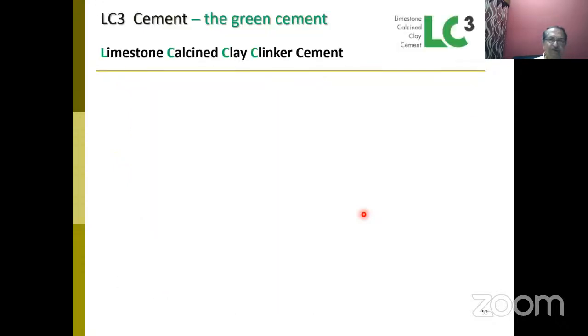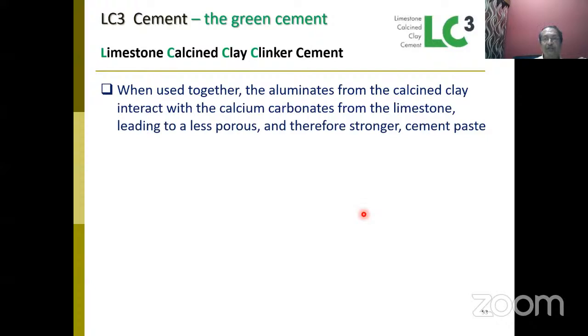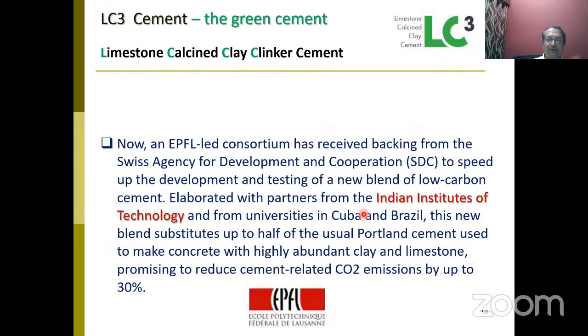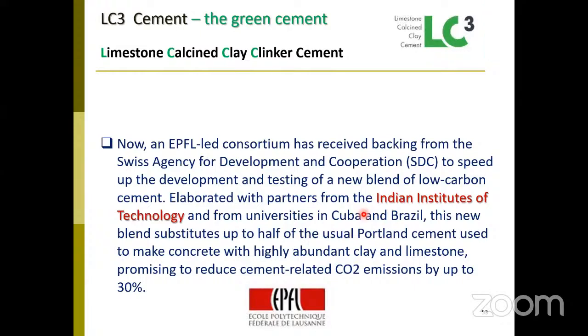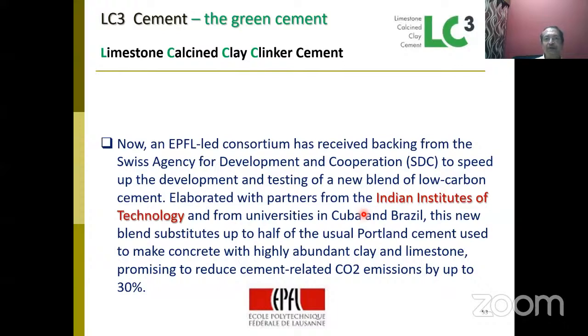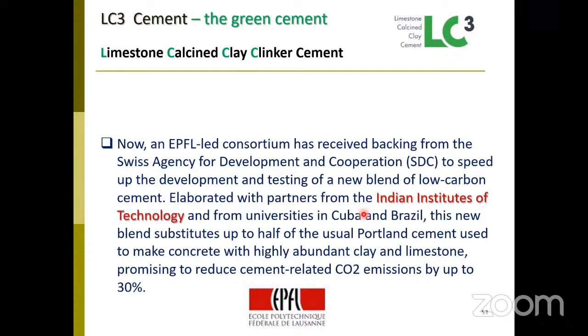Lastly, I would like to talk a few minutes on LC3, on which the BIS has already formed a working group, and the draft code for LC3 is almost ready. This is basically limestone calcined clay cement. This limestone calcined clay cement is a good combination of using calcined clay, and the clay that we use here is not the superior kaolinite kind of clay which is required for the ceramic industries and so on. Slightly lower grade clay which is now getting wasted can be incorporated here, and this calcined clay can be a very good input into the manufacture of cement.